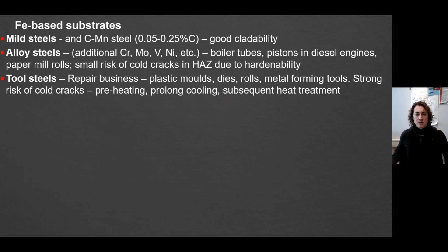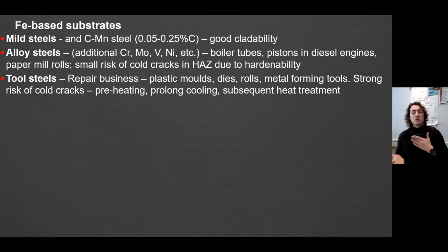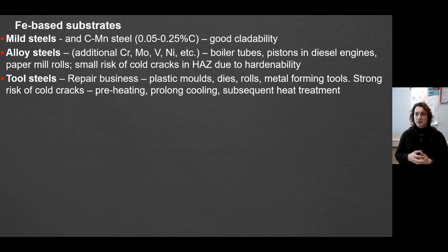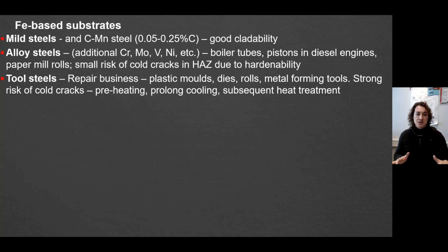It gets more complex when you go in the direction of tool steels, which are the primary repair business market. Here the risk of cracking and heat affected zone — especially cold cracks — is really serious, because you usually have to repair with hard materials. The main advice from my side is related to preheating, prolonging cooling time to ensure the right cooling conditions, and in many cases you will also need post-heat treatment.